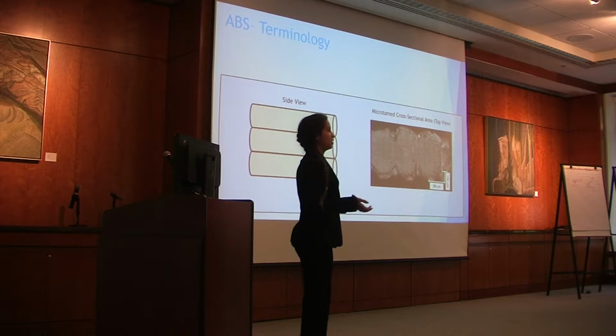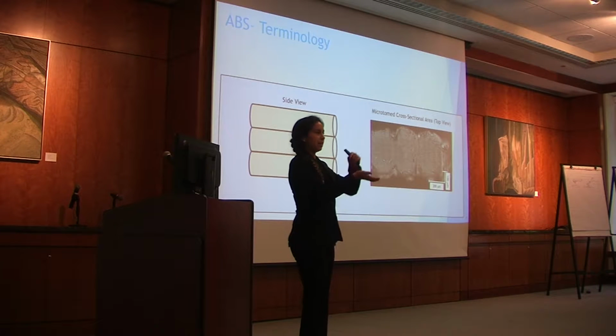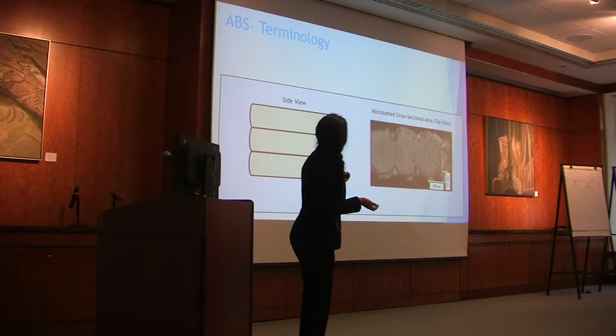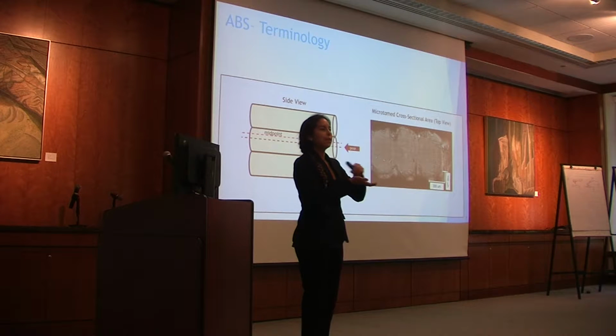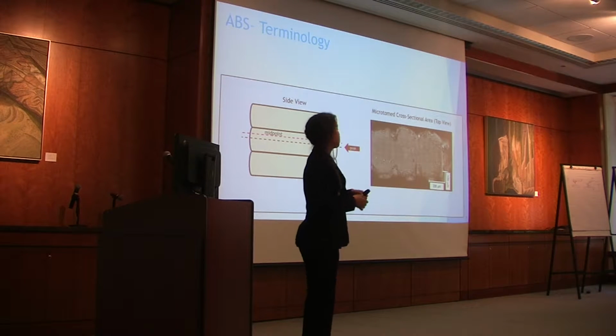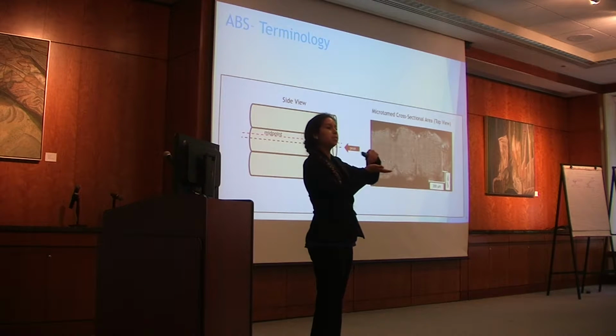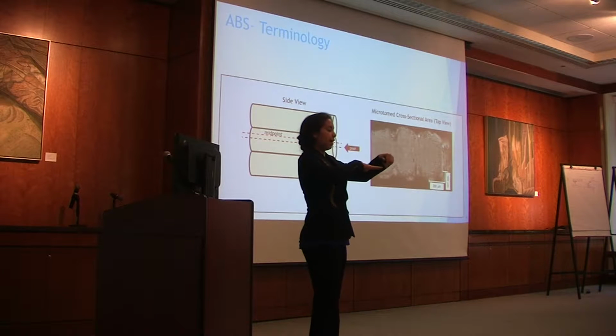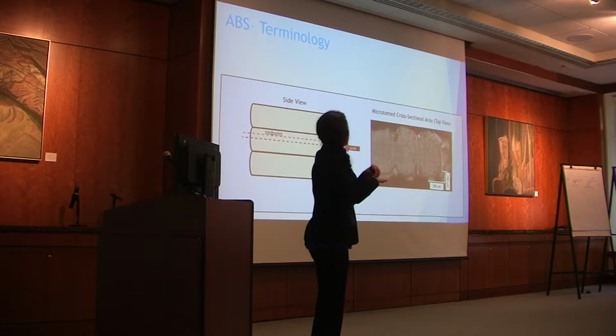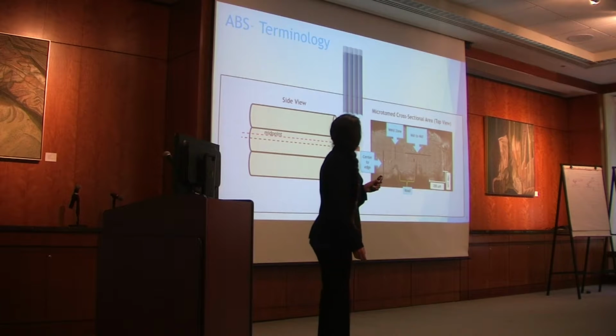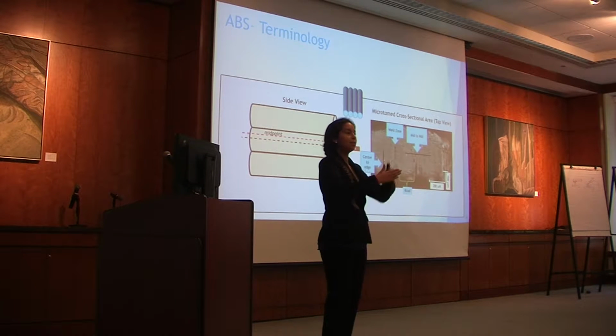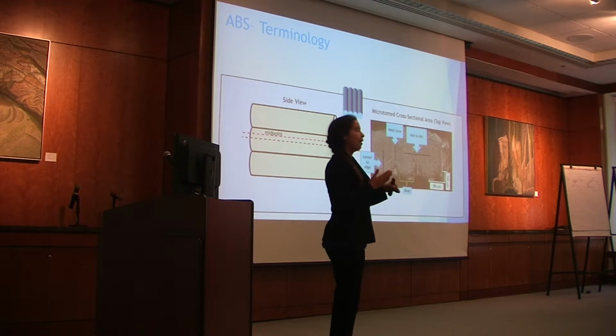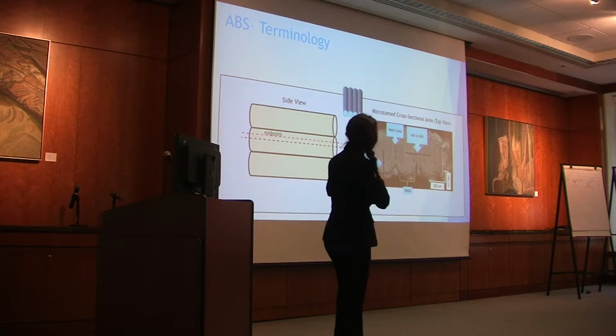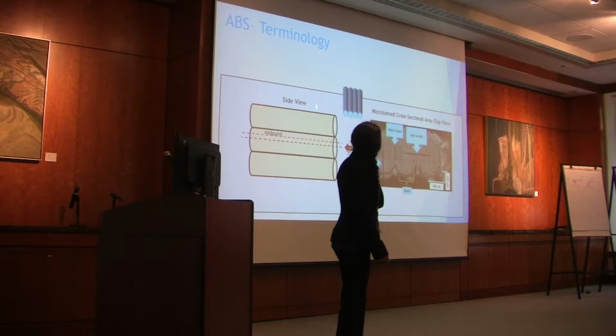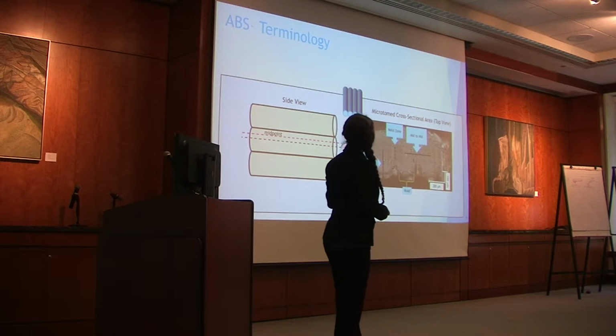So just a little terminology. The way 3D printing works, as I said earlier, is it builds layer upon layer. With this in mind, we printed a sample and then looked at this with Raman spectroscopy. We looked at two different views. We looked at a side view. So we take the sample that's printed and lay it on its side and do different line maps of that area. And then we also look at the cross-sectional area. So we take that sample, cut one side down so that it's flat, and we can look at it, and it's very nice with topography and things like that. And this is an example of how it will look laying down on the stage.